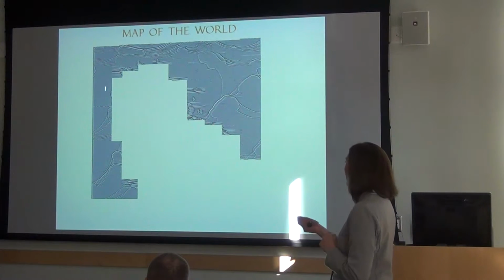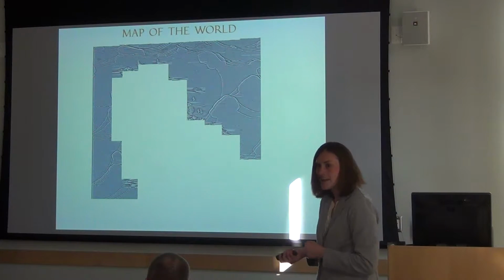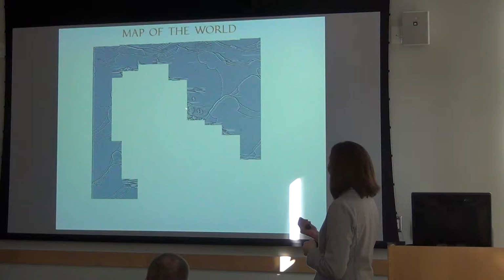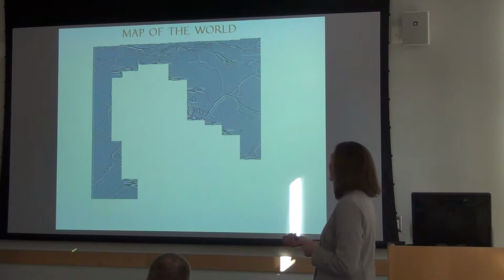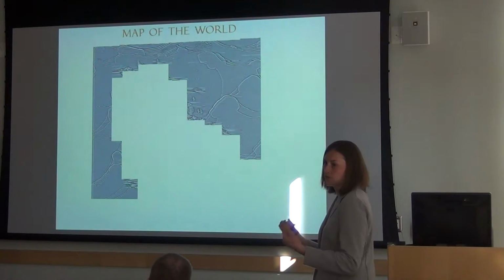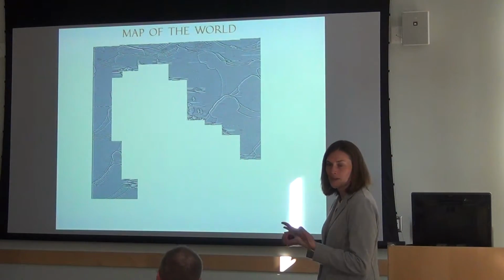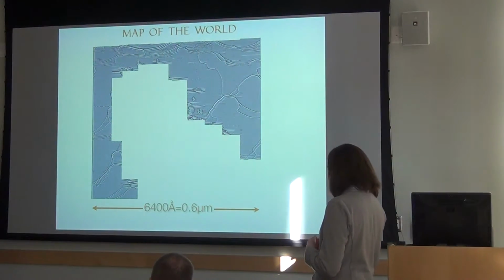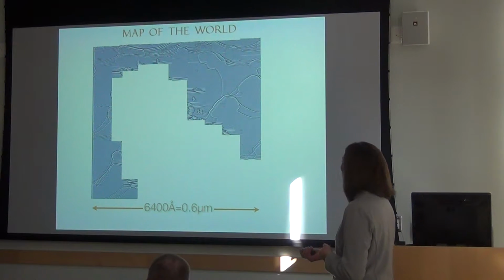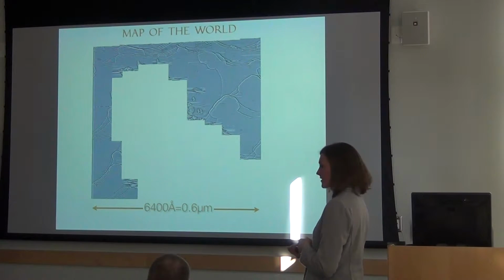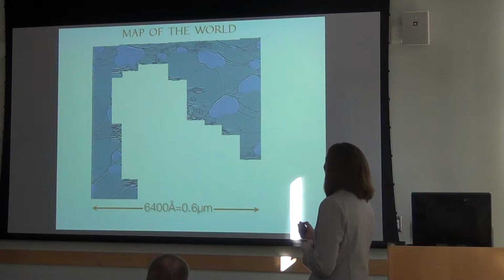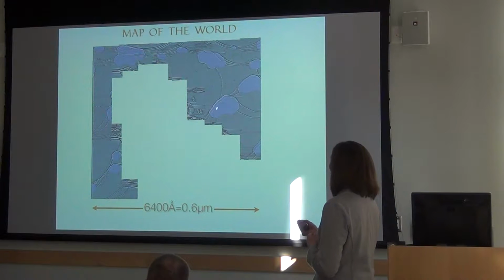And you'll notice that this entire region in the middle is empty. And that's because we started seeing these very high bumps here. And we don't want to go there because you could run into these features and destroy your tip. And then you would have a bad day. So this whole region, this whole map of the world is only 0.6 microns. And here are the graphene islands that I've shaded in purple. So they're definitely on the nanometer scale.